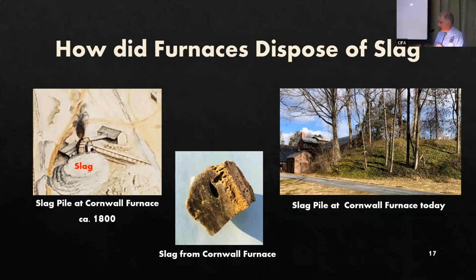Today, that slag pile you can see in the right picture, and it's covered by soil and vegetation. So it doesn't look much like slag anymore, but we're pretty sure that it's there. We're going to try to verify that in the not too distant future, but every indication is that the slag is there underneath that pile. In the middle picture, you see a piece of slag from the Cornwall furnace. And I have that piece up here if you want to look at it after the talk.